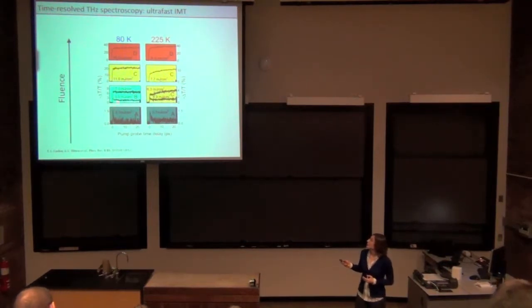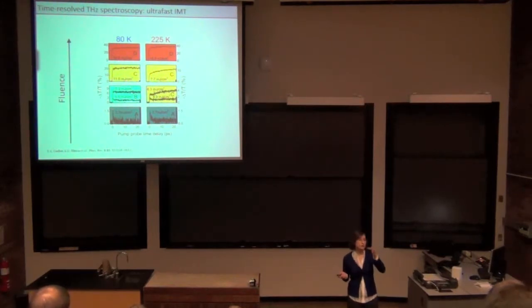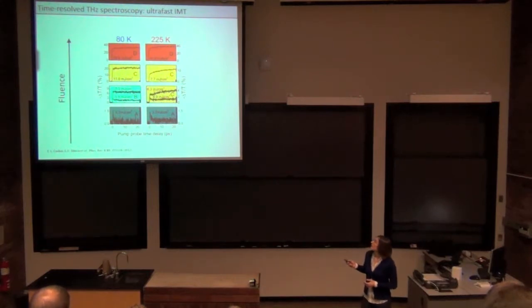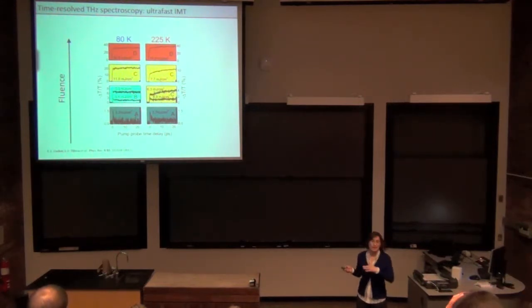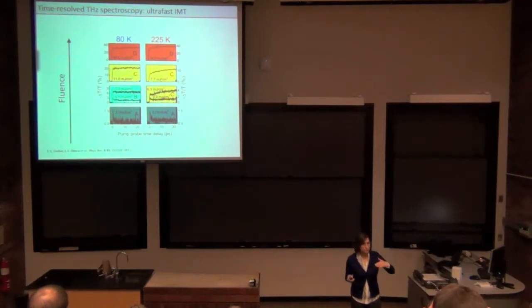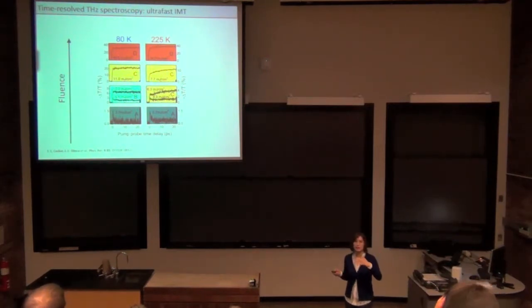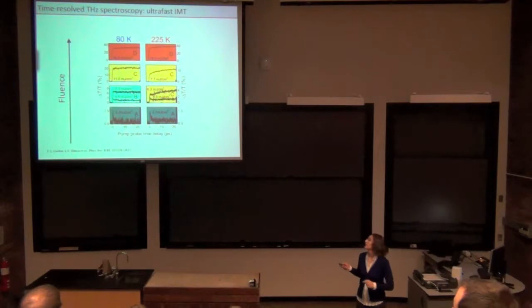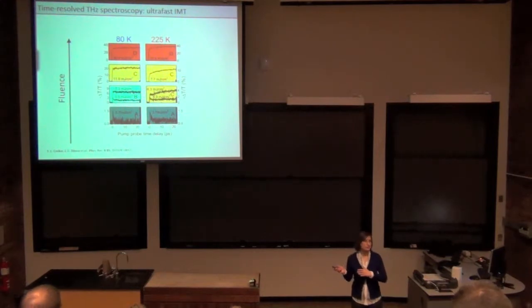In some cases, what we get is this very short-lived spike in conductivity that goes right back down. In some other cases, we get this short increase, and then the conductivity lasts for a long time, but it's quite low. We know, of course, that at the peak, when the whole film is switched, we get about 34% modulation in transmission. So here, for example, it's only 3%. It's very, very little, but it stays almost unchanging.